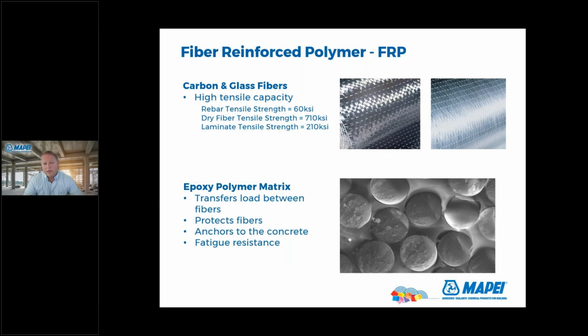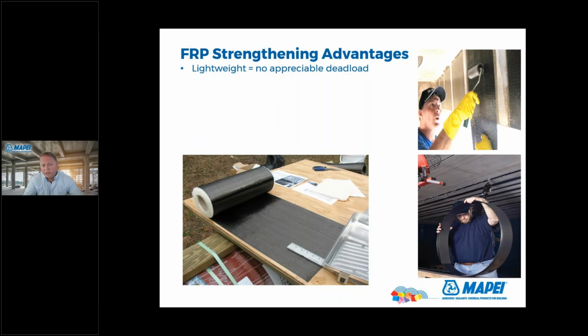And these fibers are getting saturated in an epoxy matrix. These fibers are very thin, about 1/25 the size of a human hair. And this epoxy helps transfer the load between the fibers, it protects the fibers, and most importantly, it anchors it to the concrete itself. So some advantages: FRP is very lightweight. It has a very high strength to stiffness ratio. It's non-corrosive. This is one of the miracle properties of it, especially as our existing structures are corroding. By adding additional reinforcement that will not corrode, that's a huge win.